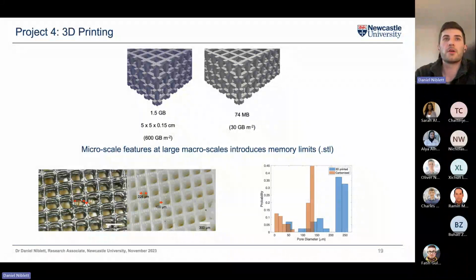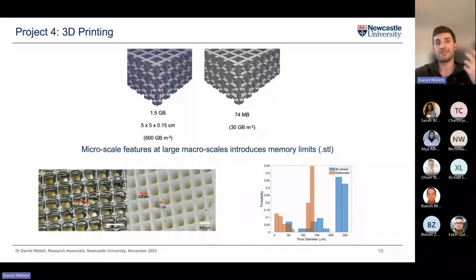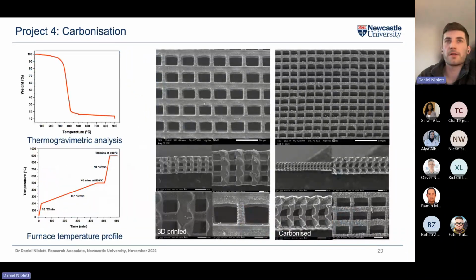And if you go through a process of 3D printing and carbonization, then you can get to sizes of around 100 micron pore size diameter and around about 25 micron fiber diameter for these cubic lattice structures. And these were able to preserve the microstructure features of turning a polymer into a carbon structure, which is needed to conduct electrons in this material. And how we did that was by carbonization.